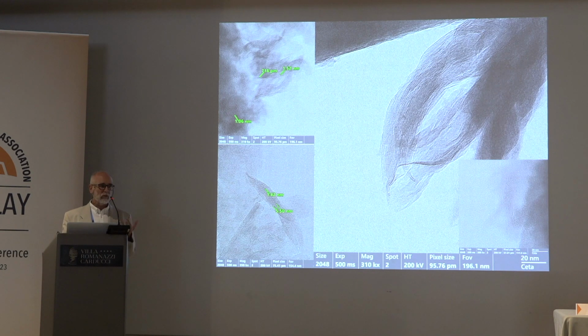And what we could observe was equidimensional irregular fragments of material. We also observed the fragment of the fibers that I showed previously, and also aggregate of flakes. And I show one of the best examples, because the most common is like this. So I think it's very low crystallinity, very small. This is a good one.